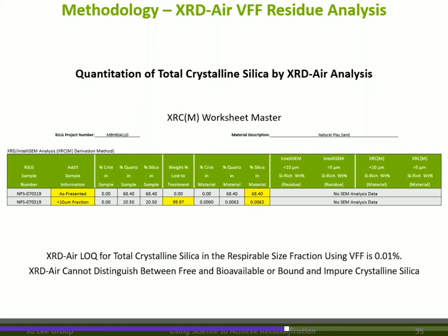When we do the back calculations with the 99.97% loss, we find that the amount of crystalline silica in that respirable residue is actually 0.006%. The XRD air LOQ for total crystalline silica in a respirable size fraction, using the VFF separation, that vacuum filter fractionation method, is 0.01. That's what we validated it to. The XRD air cannot distinguish between free and bioavailable or bound and impure. Of course, we don't care because we're already well below the 0.1%. Nevertheless, this could become important for certain materials.